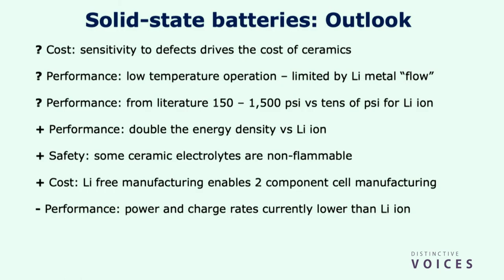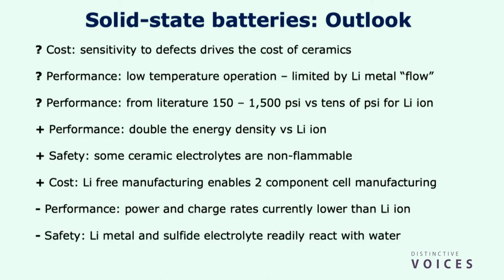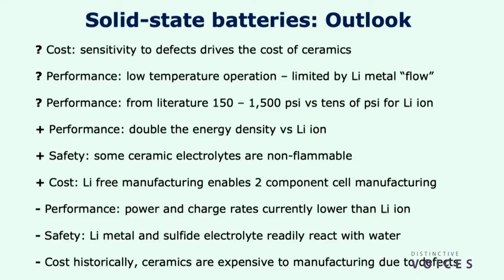Negatives, performance, the charge-discharge rates are still lower than lithium-ion, but the same amount of time and investment has not gone into solid-state batteries as it's gone to lithium-ion, so give it a chance, I say. Safety, one downside. Like the skeleton in the closet for the sulfides, they're very sensitive to moisture, so they'll form H2S gas, and that's toxic stuff. So if they're in a crash, there's water around, that is an issue. And again, just to reiterate the very first point, costs, these ceramics tend to be rather expensive. It's kind of an unknown because nobody's really made these at scale yet, so we don't know how expensive they're going to be or how cheap they're going to be.